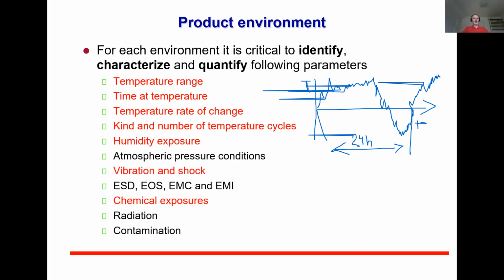Then how you quantify all these? So you have the maximum temperature, you have the minimum temperature, you have the average temperature here at high, something like X hours, and so on. So rate of temperature slope. So what is the slope here? So how fast it's going down, how fast it's going up, and then during the operational life, how many of these cycles we have, these maxi cycles and mini cycles. And in fact, rainflow counting, which I mentioned, is kind of the way to calculate exactly this. So sorry about my extremely confusing drawing, but maybe you get the point there.